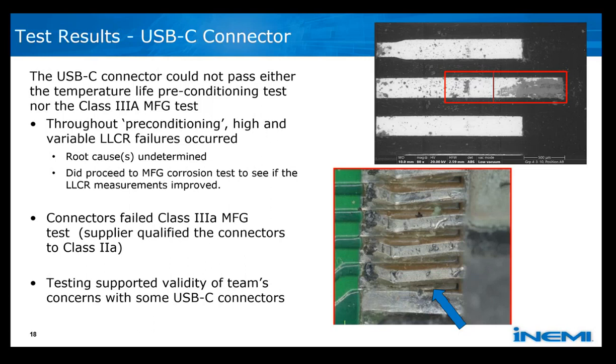On the bottom, it's a little bit hard to see, but we're trying to show with the blue arrow there that we did see occasional cracked solder joints. We had one version of the connector that was a straddle mount style contact connector. And we didn't see this during the temp life testing, but we could pick this up after the gas corrosion testing was completed. But we don't know for sure exactly when some of this might have occurred.